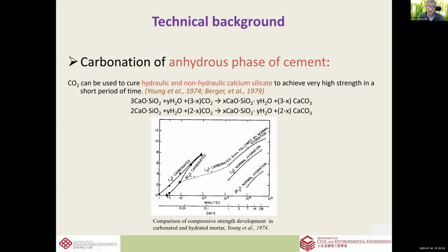researchers in concrete. They were not doing recycled material, but what they did is to carbonate the clinker phases in cement, C3S, C2S or beta C2S, which can be carbonated very quickly. The rate of carbonation is much higher than the rate of hydration. Carbonating for a few hours would be equivalent to hydrating for a month or so, producing strength. So carbonation of the clinker phases is quite well researched, and it would produce strength because of the production of calcite as well as the calcium silicate hydrates.